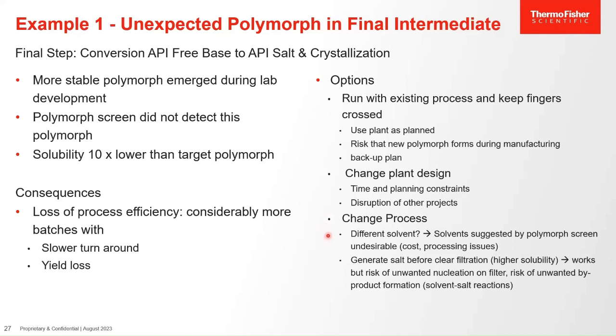You may look at different solvents. In this case, there weren't any good alternative solvents here due to solubility issues, but there may be cost issues, there may be processing issues. Or, forgot to mention this at the start, you could try to generate a different solid form, and in this particular case, we are converting an API from its free base to a salt. So you can try and convert to the salt before you carry out a clear filtration. The final API crystallization has to have a clear filtration to avoid particulates, and try to use the higher solubility of the salt to counter the lower solubility of the new form.